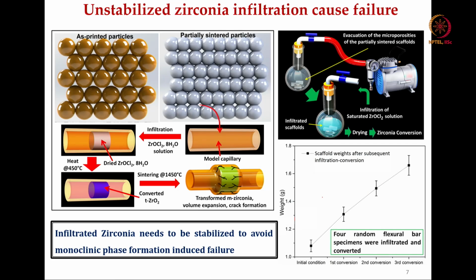So, let me just show you the approaches that we have used. First, if you use unstabilized zirconia, like 0 mole percent zirconia, and infiltrate it into the zirconia powder bed, we have seen that it causes failure. We have prepared a small experimental setup.